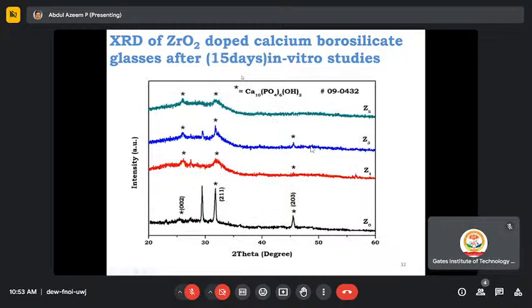Similarly, this is the XRD of your material recorded after 15 days of time. See, the peak intensity is increasing. That means the crystallinity is increasing.